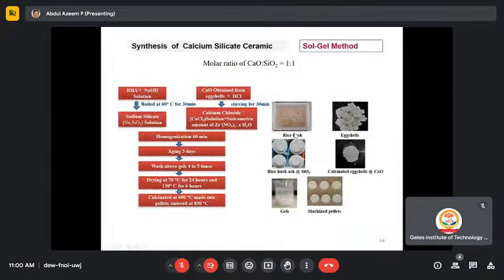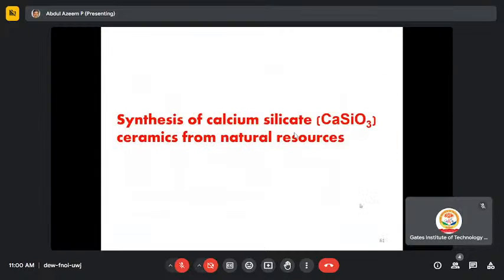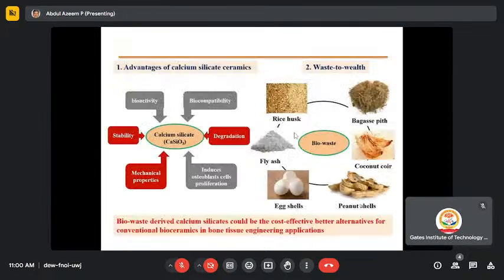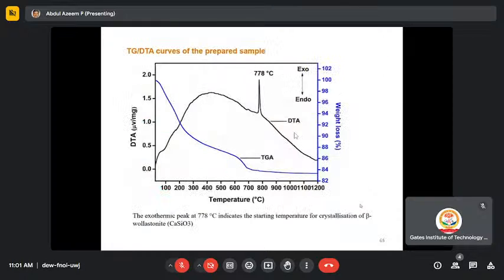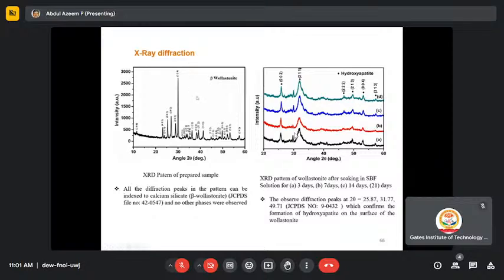So this is the protocol we followed, and we developed the material. For this we got the Indian patent in 2021. With the help of this method, we developed the calcium silicate, and this is the TGA, which tells the crystalline temperature of a material. By optimizing the temperature, we got the structure, which is a crystalline material. This is the XRD, which confirms the material is crystalline in nature.